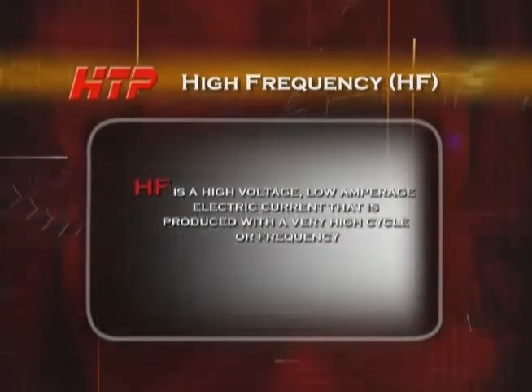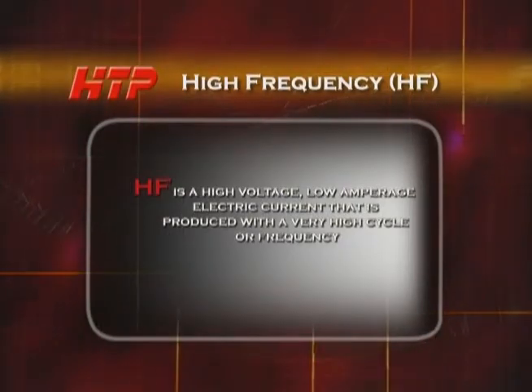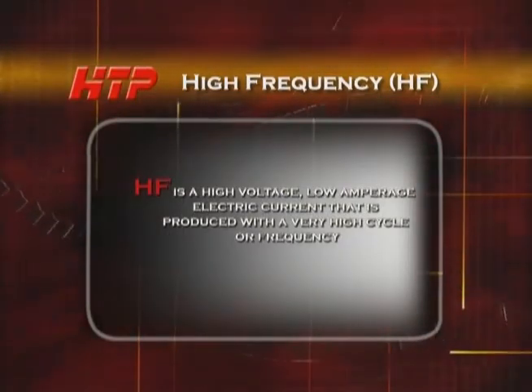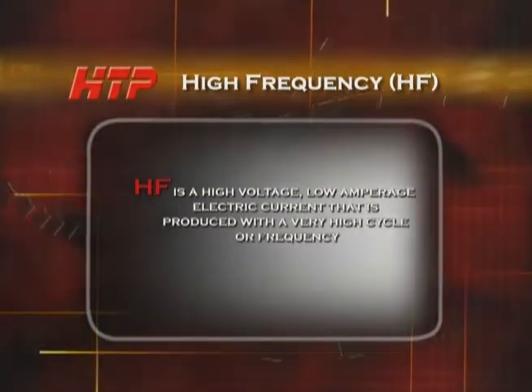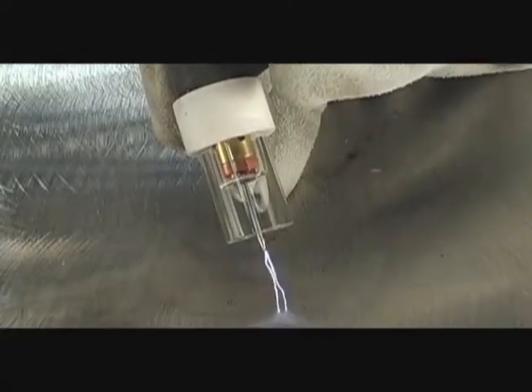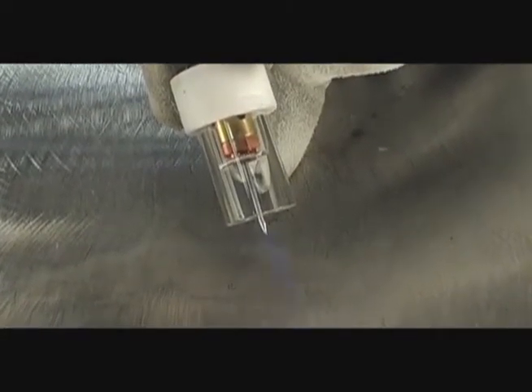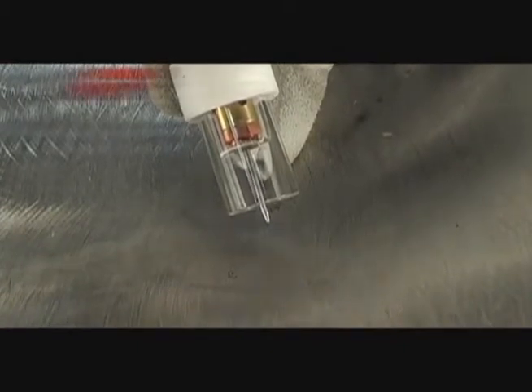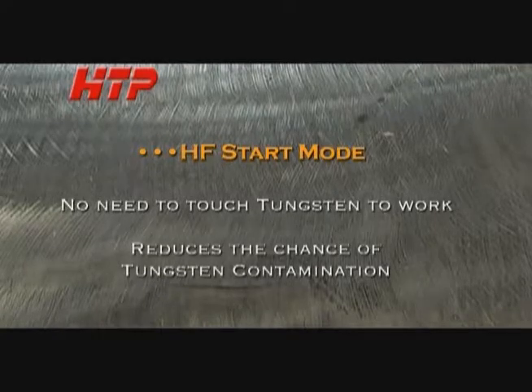HF is a high voltage, low amperage electric current that is produced with a very high cycle or frequency. The HF arc is like a spark plug arc. It jumps the air gap between the tungsten and the workpiece to get the arc started so you don't have to touch the tungsten to the work, which eliminates the chance of tungsten contamination.